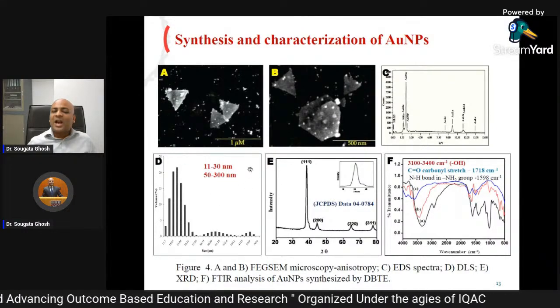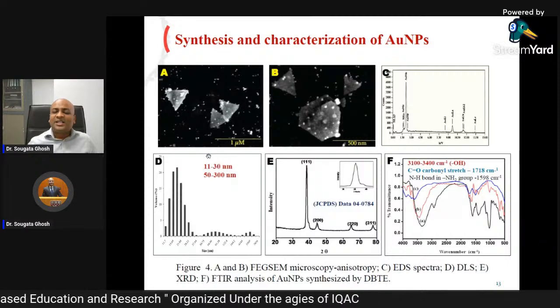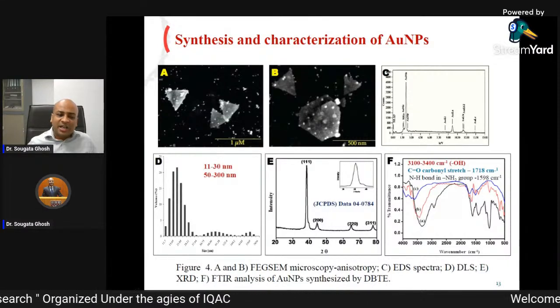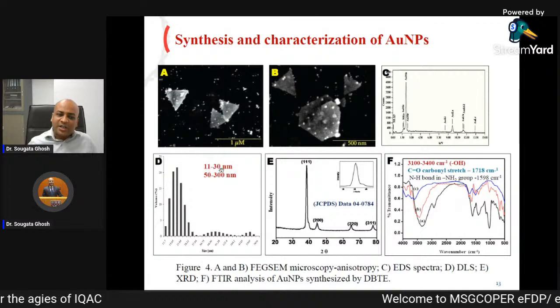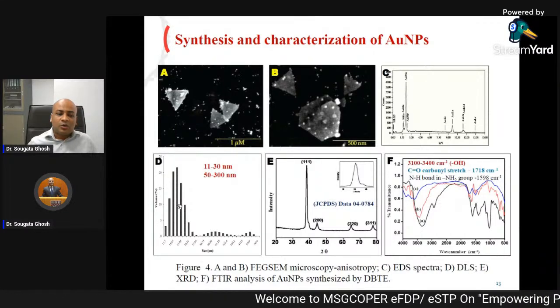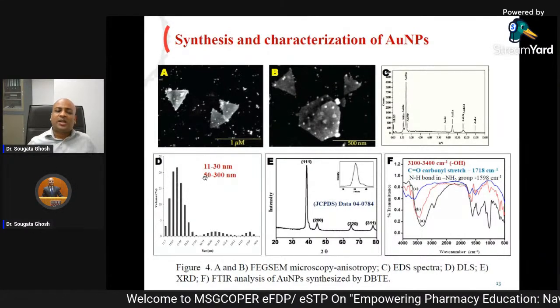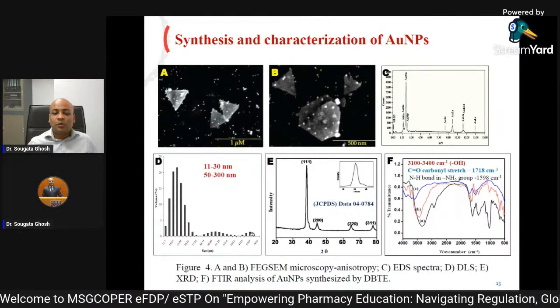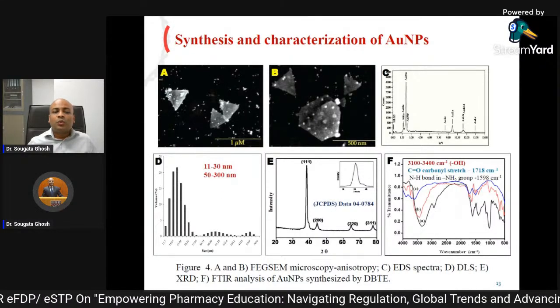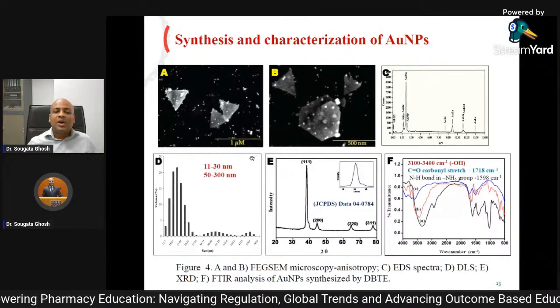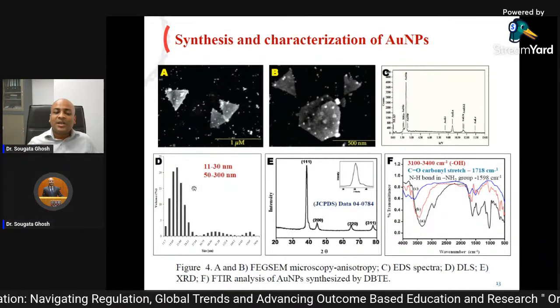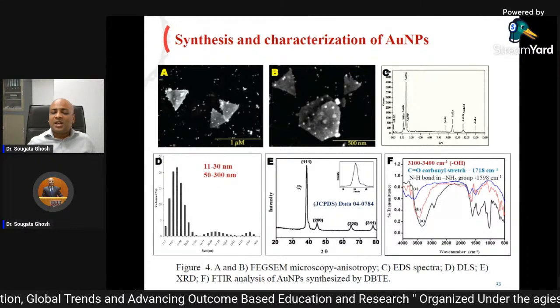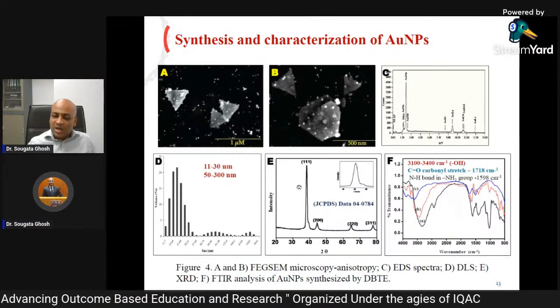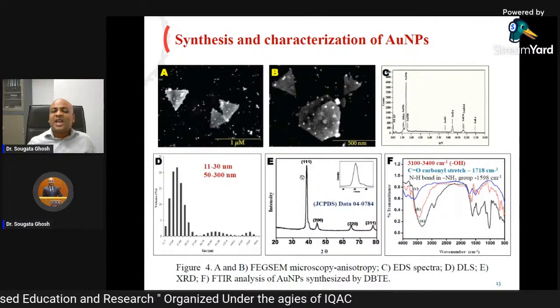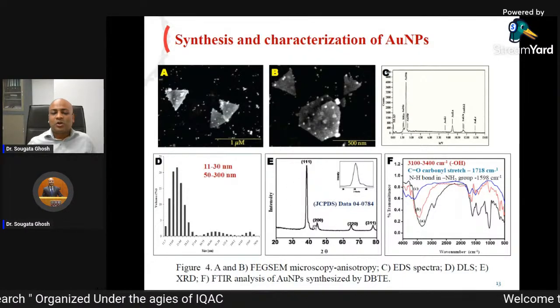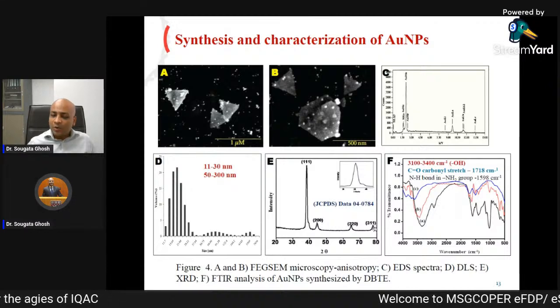What was the diameter of the nanoparticle? So there is a process called dynamic light scattering, DLS. And we found that there are very small nanoparticles around 11 to 30 nanometer over here, and there are some bigger nanoparticles, 50 to 300 nanometers over here. So what we could see in the FESEM was matching with the DLS. Next, another method to see the purity and crystallinity of the gold nanoparticle is XRD, and this XRD spectra was also giving signature peaks of gold nanoparticle.